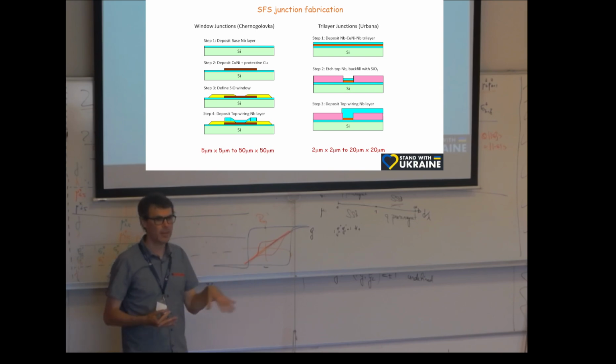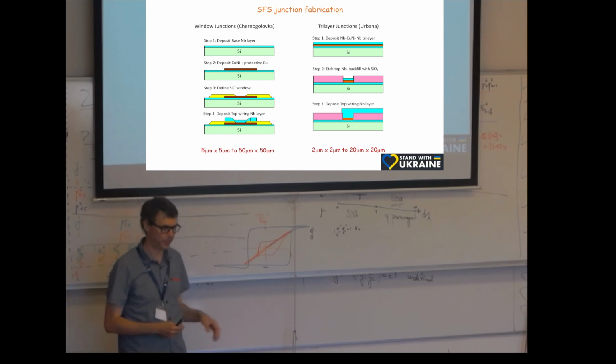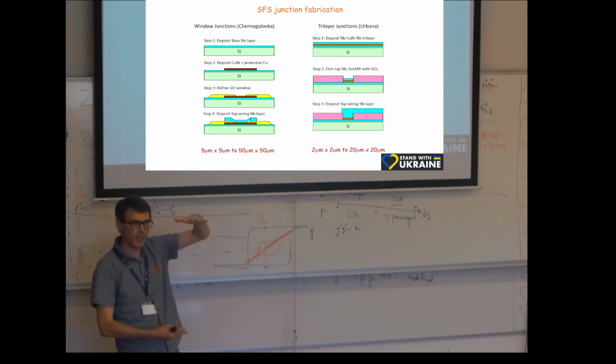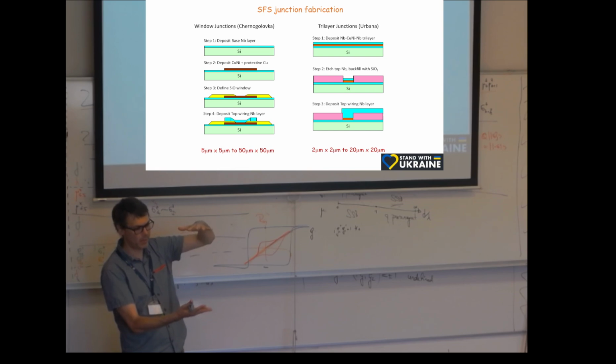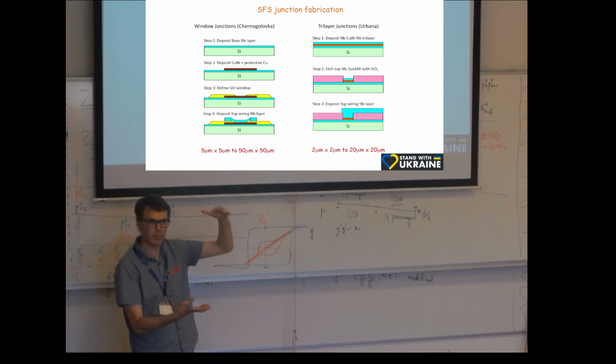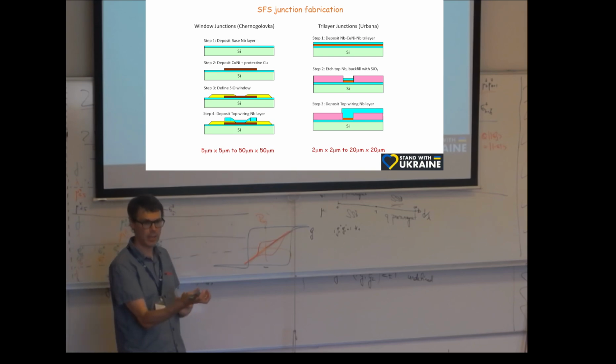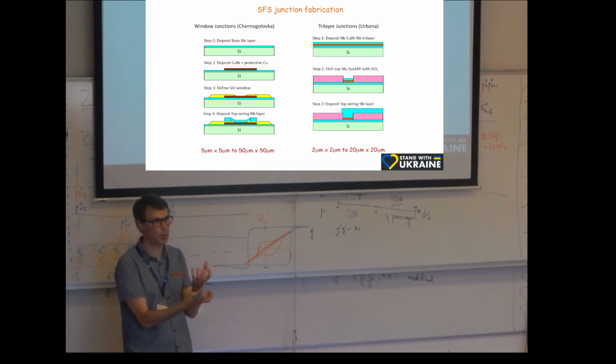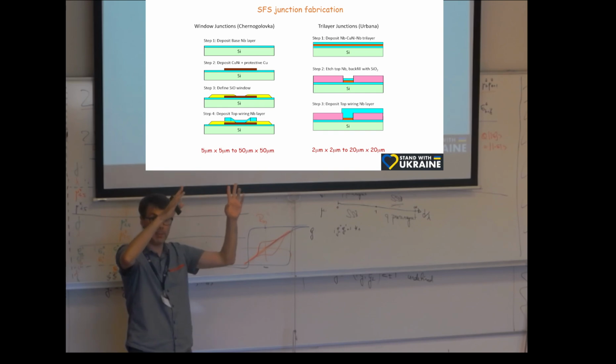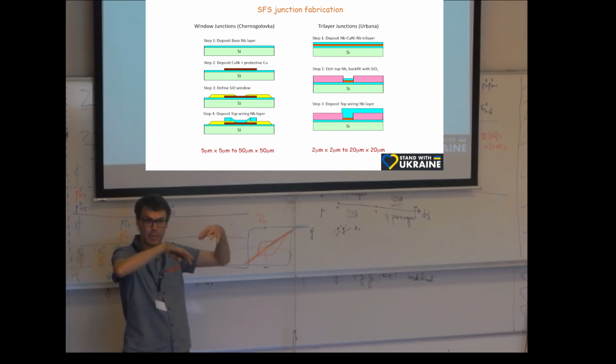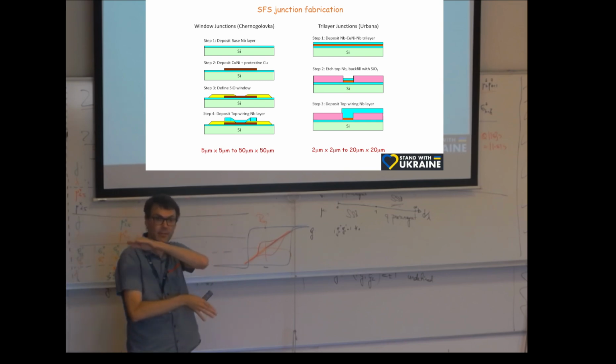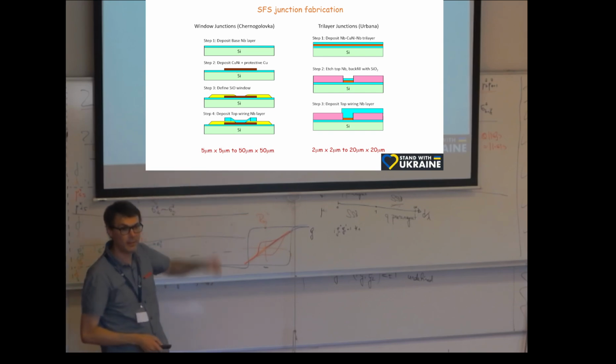Yeah, so now it's popular to put flakes of boron nitride as a dielectric, but we didn't have that, right? So you put the substrate upside down usually, and below it you make either, so the easiest one to explain is electron beam evaporation, right? So you have a boat, and then you shoot electrons at it, and you heat up the boat with high energy, melt the metal in it, and it starts to evaporate. And because it's in vacuum, it doesn't evaporate like steam from your cappuccino, but the atoms go in straight lines, and they make very smooth films. And this is how thin film processing is done.